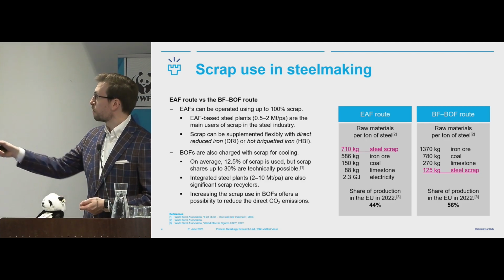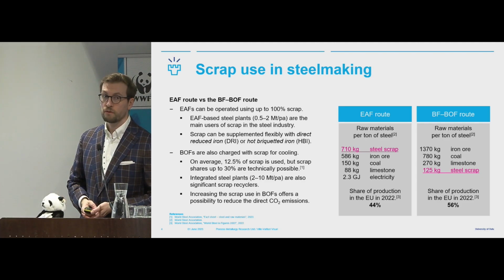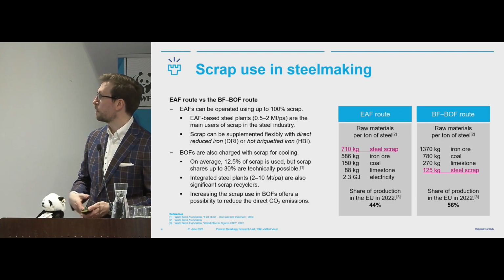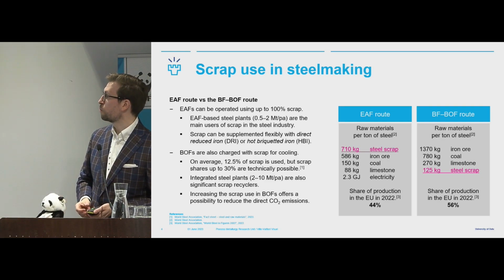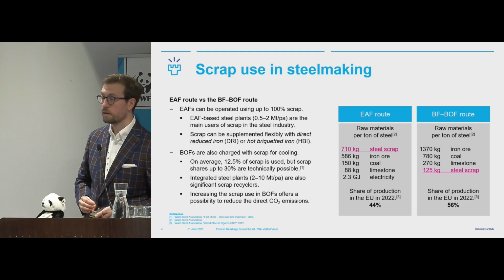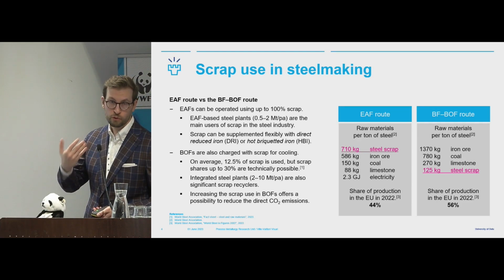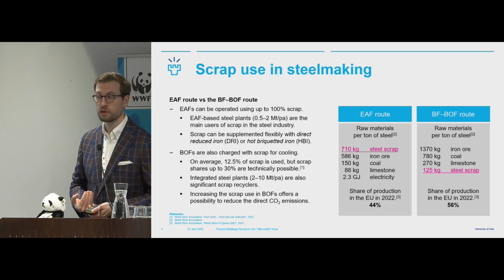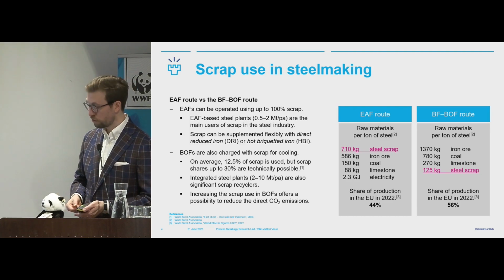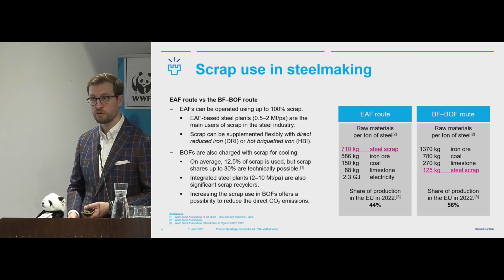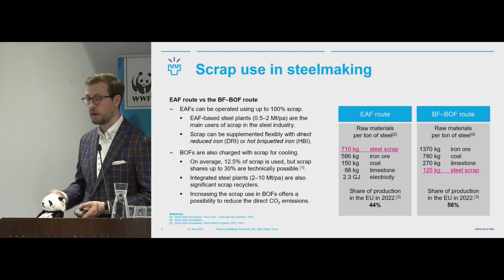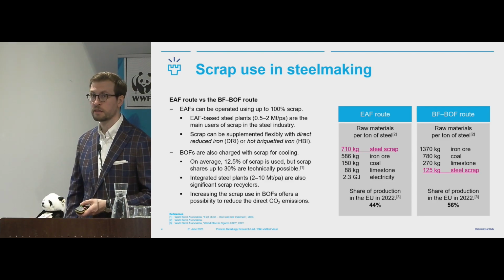And here on the right, we see typical consumptions for these different routes, and we see that in the blast furnace BOF route, we use quite a lot of coal and limestone. Also, the production of limestone induces CO2 emissions. And if we use more scrap, then we directly reduce these emissions and also the emissions related to the materials.